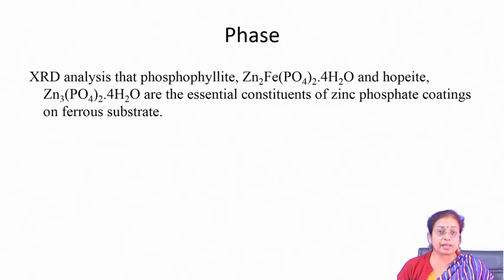Usually, depending on the kind of phosphate solution you are using, there may be zinc phosphate or manganese phosphate, or iron phosphate forms, or zinc iron phosphate forms. So, the kind of phases which are forming on the surface depends on the kind of solution you are using for phosphating, and this particular phosphating operation is not only good for improving the paint adherence or colorizing the surface,